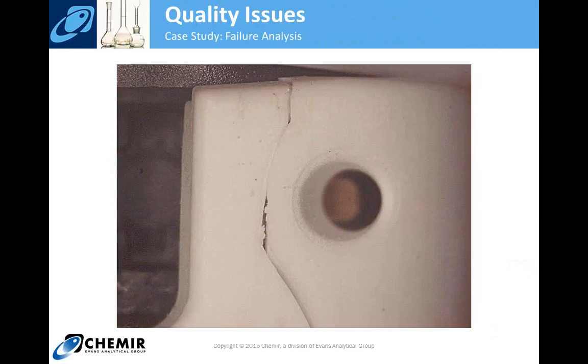When the cracking occurred, it was no longer able to hold the tension and support the bulbs in the fixtures, and so the bulbs were falling down. So this is what was being noted: this type of cracking in the tombstone. And curiously, this was only an issue with one specific client. It was a very big client of our client, but the issue was unique to just that one client. That made it very interesting, as to why this failure was happening with one client but not with others.